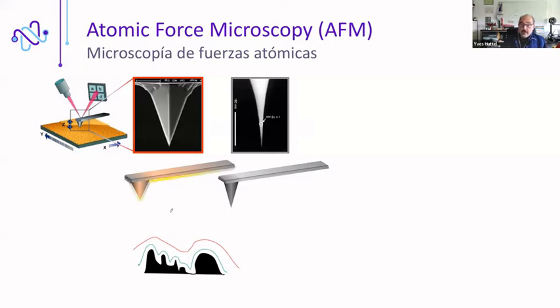Another problem is that you might be interested in making images of the morphology of your surface, but you will probably also be interested in measuring the magnetic properties of your surface or the electrical potential of your surfaces or the hardness of your surfaces and so on. There are many, many applications of this microscopy. And in order to make this other type of measurements like the magnetic measurements, you have to functionalize your tip by depositing a magnetic coating, for example. And when you deposit the coating, you increase the size of the apex of your tip. So the resolution becomes worse.